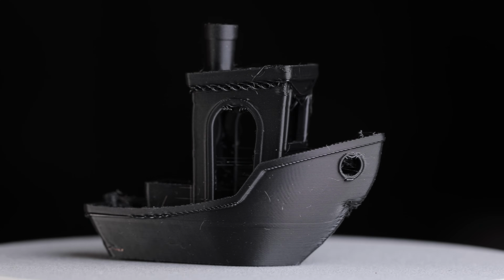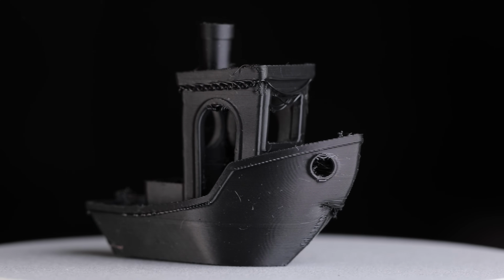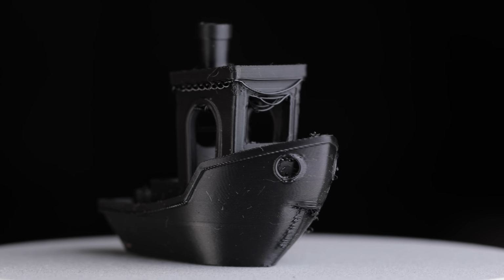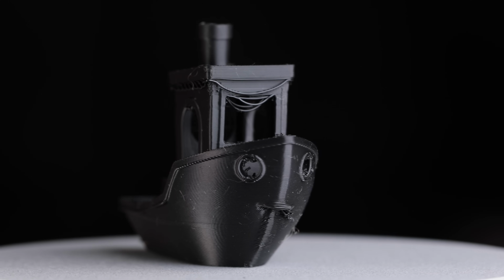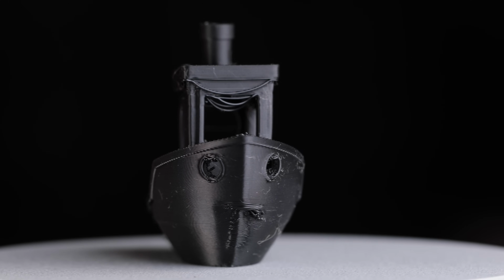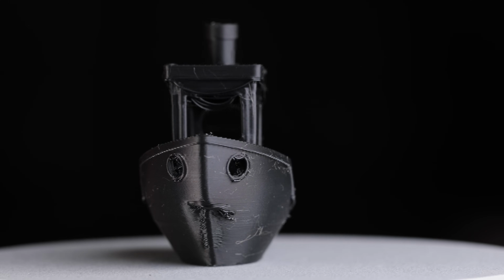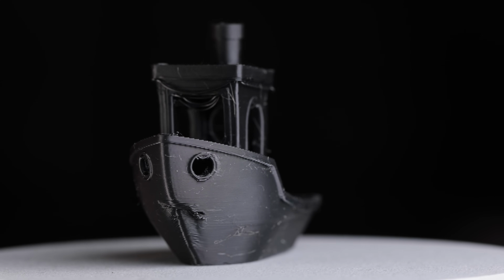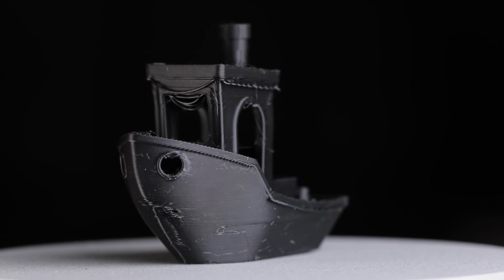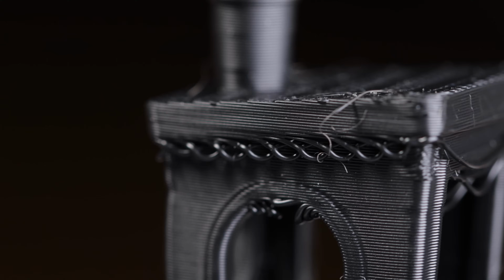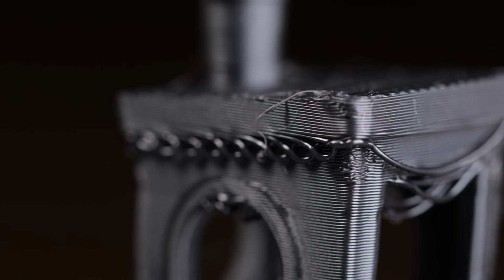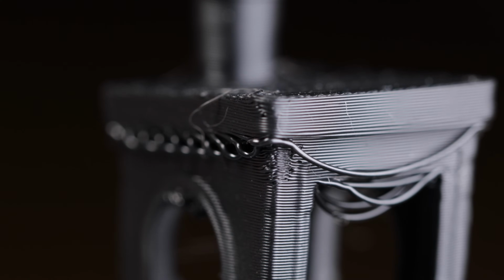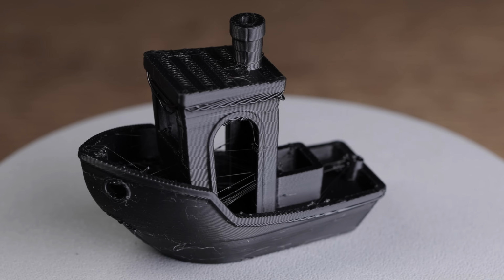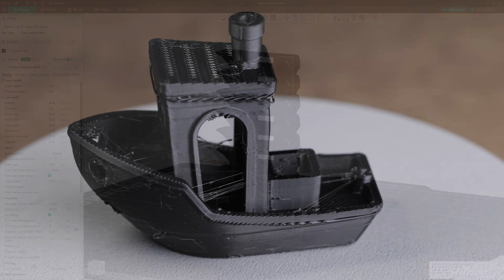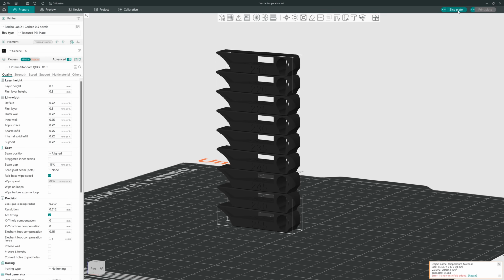As for my first print, a benchy, well, it didn't look great. The bow area shows clear signs of poor adhesion to the lower layer. It seems the filament is pulled back by the nozzle. We should probably increase the temperature and print more slowly. Looking at the roof overhangs, you can also see that the filament isn't bonding properly to the layers below. And last but not least, there's some slight stringing. For these reasons, I decided to print a temp tower.